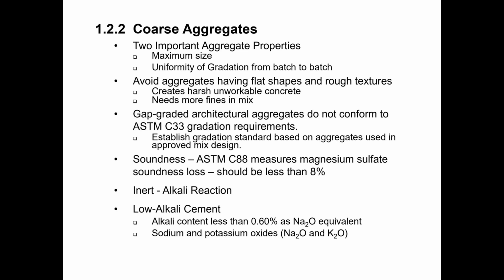Sometimes we use coarse aggregates that do not have a nice smooth gradation curve. We refer to these as gap graded aggregates. So these gap graded aggregates generally will not conform to ASTM C33 gradation requirements. Conformance to ASTM C33 is a common specification requirement, but to achieve the aesthetics that are desired for an architectural precast unit, sometimes we may have to use an aggregate that does not meet C33 gradation requirements. Generally, that's going to be okay.